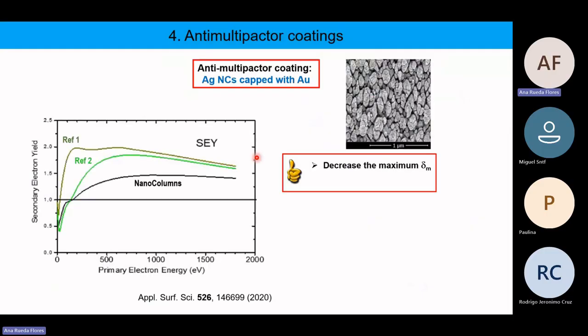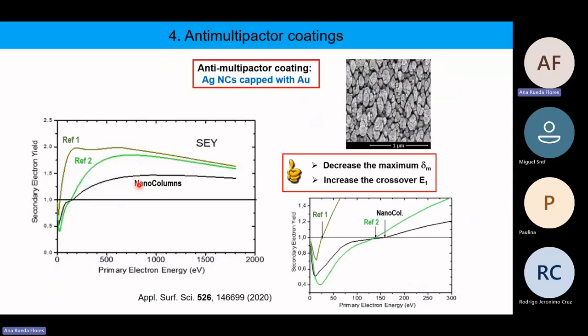So, here I am comparing the secondary electron emission yield curves in black for this coating, and in green for two reference materials used in the aerospace industry. So you can see that the first characteristic that we wanted to achieve, the decrease of the maximum, is clear. And now we will focus our attention on the low energy part. You can see that the coating with the highest crossover energy is the one with the nanocolumns. So we have increased the range in which we have less than one secondary electron emitted per primary electron. So that is the other characteristic that we wanted to achieve.